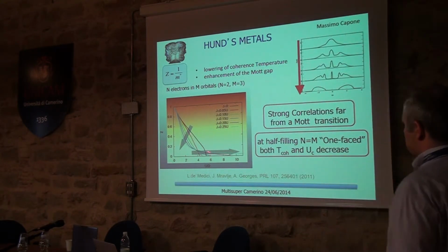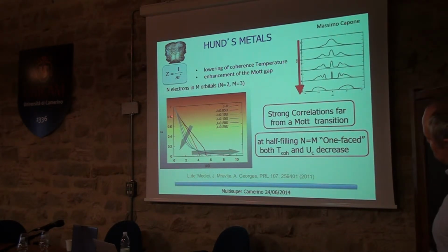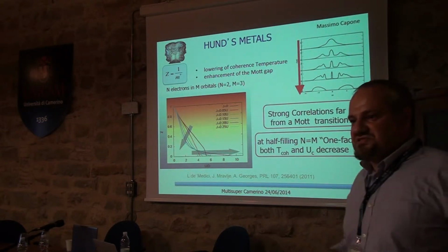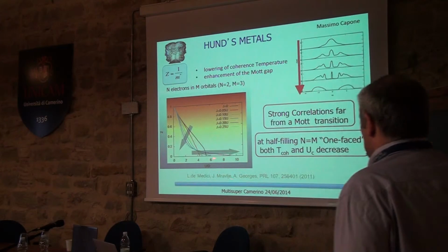So what happens when you introduce the Hund's coupling? Say the black line would be this scenario here. This is our Z, you increase U, and it goes more or less gently to 0. Without particular scales, you go to 0 at some value of U. And that's the Mott-Hubbard transition that we know.